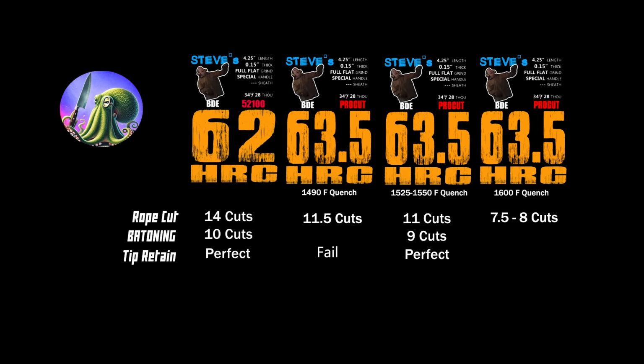Here's my compiled results I was telling you about. On the left is the 52100 at 62 HRC. The three results to the right are all ProCut at different quench temperatures, 1490, 1525, and 1550, and then 1600 degrees Fahrenheit. As you can see, as we go up in quench temperature, we do in fact seem to lose some edge retention. And then I think you could argue on the other side that the lower, probably the less tough it is. All right, so those are my results in my shop.